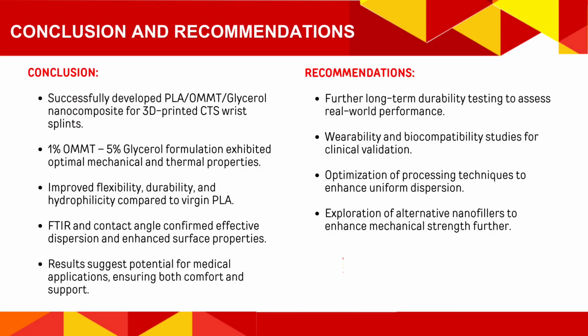To conclude, this study successfully developed PLA nanoclay glycerol nanocomposites for 3D printed wrist splints, optimizing comfort, flexibility, and durability. The 1% nanoclay and 5% glycerol formulation exhibited the best balance of mechanical strength and flexibility, making it the most suitable candidate. Thermal stability, improved hydrophilicity, and effective dispersion of nanoclay and glycerol further validated its potential for biomedical applications. To enhance its performance, we recommend additional mechanical testing for long-term durability, wearability and biocompatibility assessments for real-world use, optimized processing techniques for better nanoclay dispersion, and exploring additional additives for improved functionality.